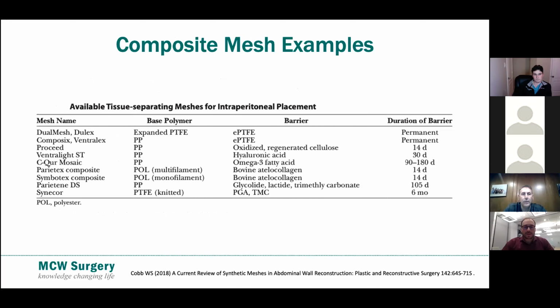So just looking at some of the composite mesh examples here. On the right of the screen, you can see some of the timelines that these barriers last. PTFE lasting indefinitely, then the regenerated cellulose lasting just 2 weeks, whereas the polyglycolic acid trimethylene carbonate construct lasting up to 6 months. And then when looking at some of the base polymers here, this is just some examples of how the different materials can be manipulated. So PTFE, you have both an expanded PTFE base polymer, and then in the case of Synecor, it's a knitted PTFE. Parietex and Symbotex are both examples of the different multifilament versus monofilament constructs of polyester, and then you have a variety of polypropylene.